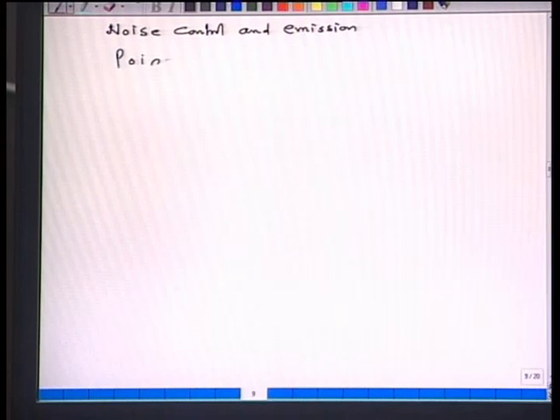So, one of the most important considerations in case of electric arc furnace is to control the noise. Another, say you have poisonous carbon monoxide, for which one is to take sufficient measures, then toxic NOx, because under the action of the arc, if some infiltrated air is there, then nitrogen can decompose to N and it may react with O to form NO. So, that may form the NOx, and that is a very poisonous gas. Now, in this particular case, possibly foaming slag practice will be very good, because then the arc will be submerged in the foaming slag, and whatever air is infiltrated into the electric arc furnace will not come into contact with the arc.